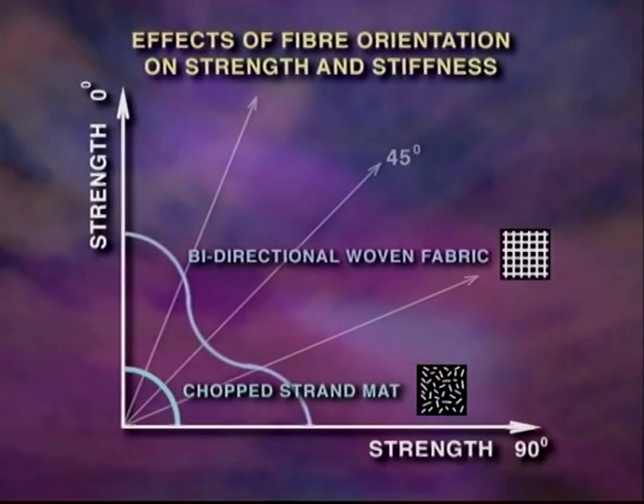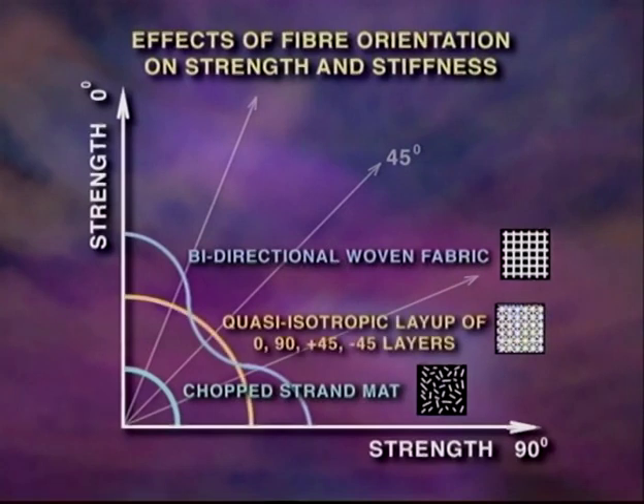If the strength for a bidirectional woven cloth is plotted, there will be a dip in strength at 45 degrees, as there are no fibres in this direction. If another layer is added, such that its fibres are at 45 and minus 45 degrees, then its maximum strength will be less due to increased section, but will be the same in all directions.